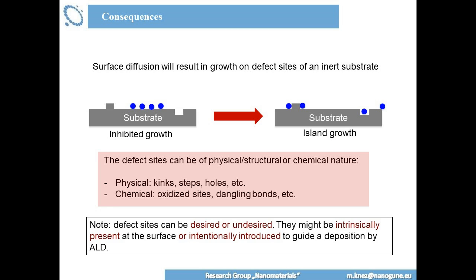Again, sketching here what this means. Your precursor molecules will come to a surface. The surface is not ideal. It may have steps, it may have kinks, it may have physical or chemical functional sites. Upon inserting enough temperature or thermal energy, those physisorbed molecules will start to move around. They will go to those edges, the steps, chemical or physical defects, and start growing around there. And what kind of defects you may have is just outlined here, so you have kinks and steps or chemical functionalities.